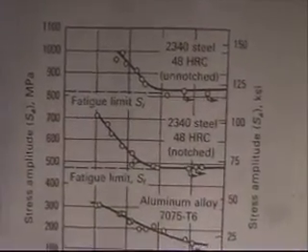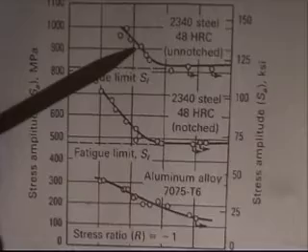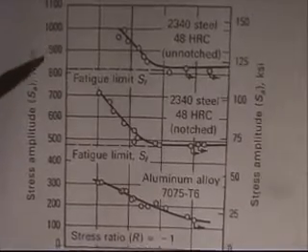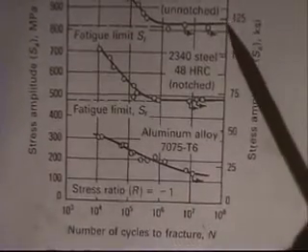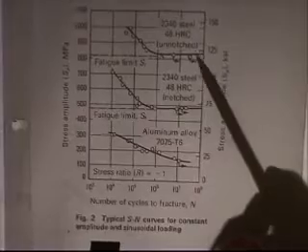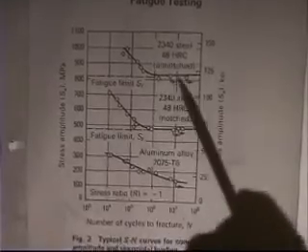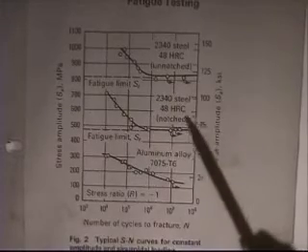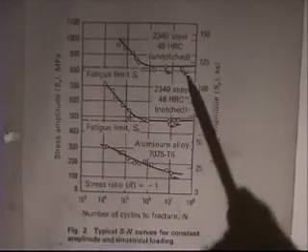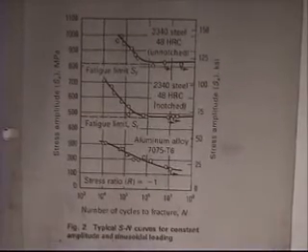If you're talking about aluminum alloy, they haven't changed the origin. This is on the same scale. So a high strength steel, which 700 megapascals is 100 KSI. Okay, 100. So if you go over, you're at 125 KSI fatigue limit. That's a pretty high strength steel. This is not landing gear type of steel, but it's approaching the type of strength level that you'd have in a landing gear for an aircraft. Here, if you put a notch in it, you can drop your allowable stress by 40%. So someone takes a high strength piece of steel and you put a file notch in it, you're liable to